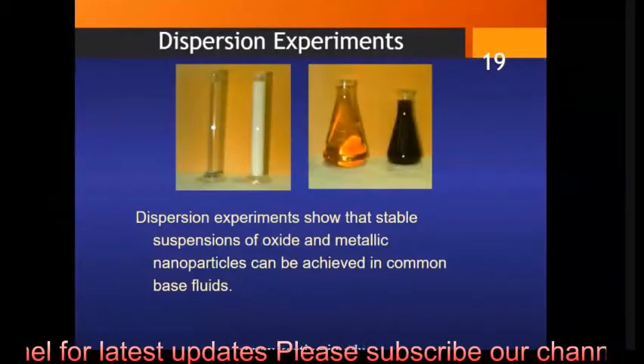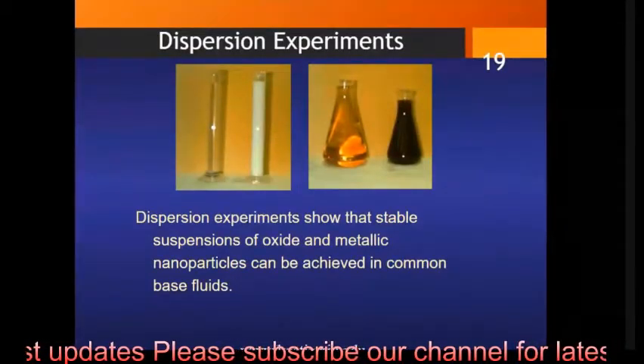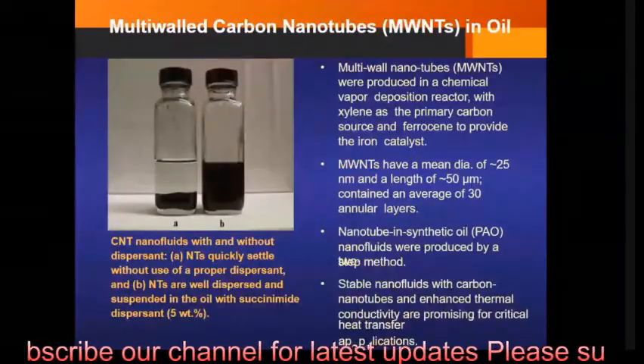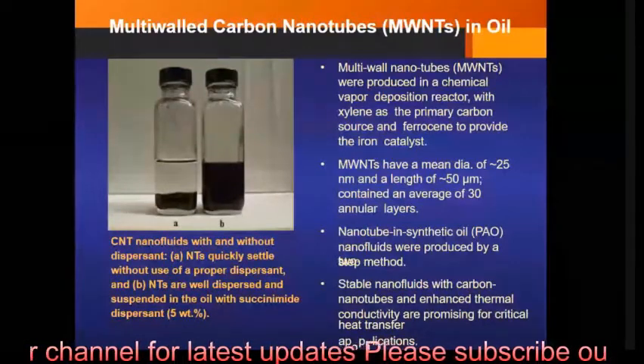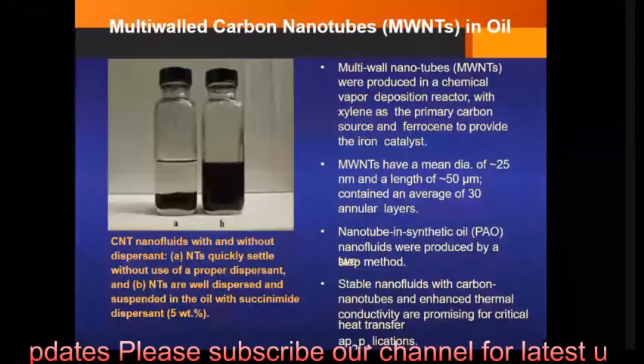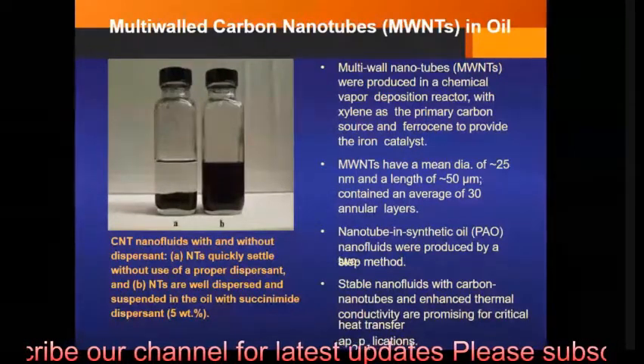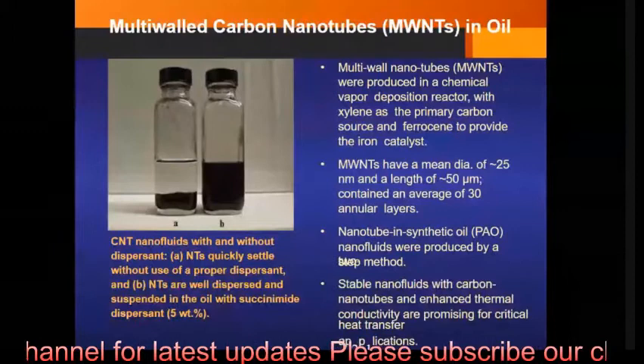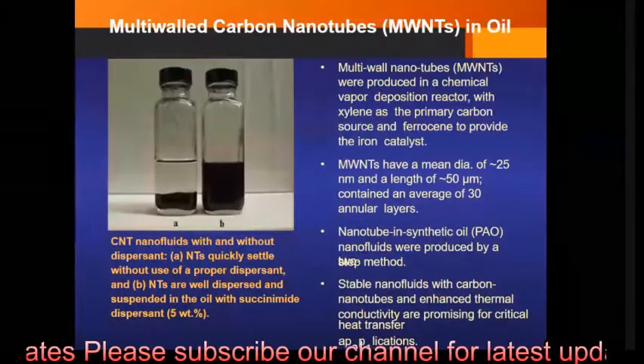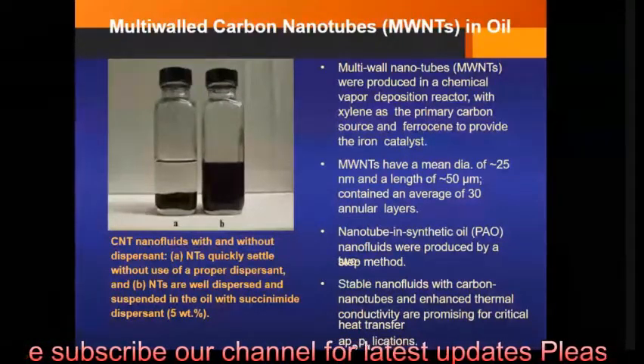And if you have a look at the dispersion experiment, it shows a stable suspension of oxide and metallic nanoparticles, and it can be achieved in common base fluids too. So next one is multi-walled carbon nanotubes in oil. Multi-walled nanotubes were produced in a chemical vapor deposition reactor with xylene as the primary carbon source and ferrocene to provide the iron catalyst. And it has a mean diameter of approximately 25 nanometer and a length of approximately 50 micrometer, containing an average of